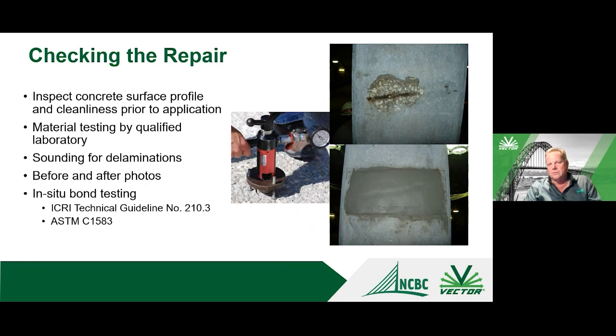You can either test the substrate just to see what the direct tensile strength of the concrete substrate is, or, probably a little bit more commonly, you would core through a repair into the base substrate and glue a disc on and directly pull it off and see where it breaks. Does it break in the repair material, at the bond line, or in the substrate, and what is the force that pulls it off? So that's a good in situ quality control method.